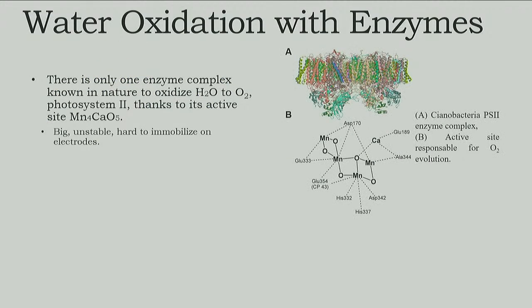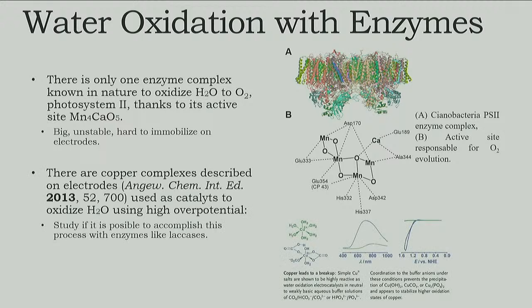In nature, we only find this enzyme here, photosystem 2, that is able to produce oxygen. It has a lot of subunits, and this is the cluster of the active site of photosystem 2, and it's very big. It's unstable. It only lasts like half an hour, and it's very difficult to immobilize on electrodes. And searching in the literature, we found that there are copper complexes described that can be used for water oxidation. And they could use them, applying a large potential for these complexes.